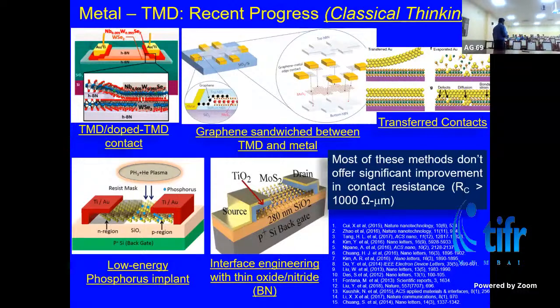Right? So, what happens in bulk semiconductor to balance this charge and ensure there is no charge transfer is basically then kind of affects the Fermi level and Fermi level pins. So you cannot have efficient charge transfer, and you have a big barrier built in. So what is done in bulk semiconductor? You basically dope that region. So doping that region means you're increasing mobile charge concentration in that region where you want to make contact.